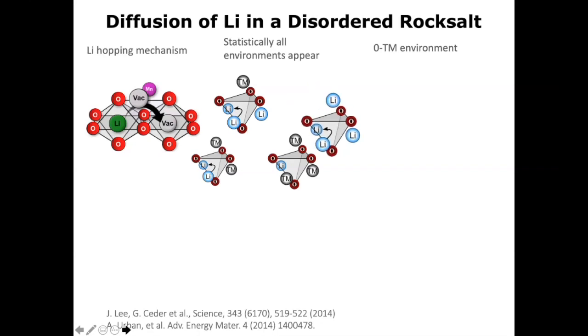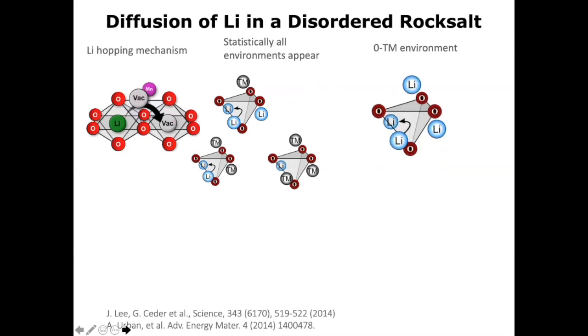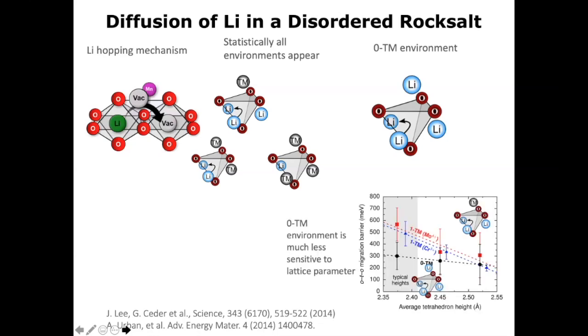And in layered materials, you don't have these environments, but when you make lithium excess materials or where you disorder, you will statistically get all kinds of environments. So some of these will appear. And indeed, they have lower activation energy as a function of tetrahedron height. The black line is this zero TM channel, as we call it. The red and the blue lines are this one transition metal channel. And an important thing is that this zero TM channel, the activation energy through it is much less sensitive to the size of the tetrahedron. So that means you can make more compact structures and still have good diffusion.